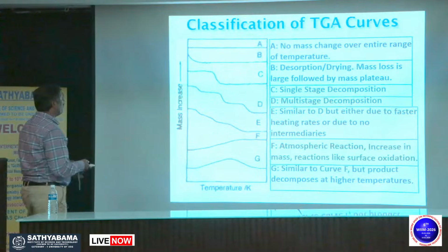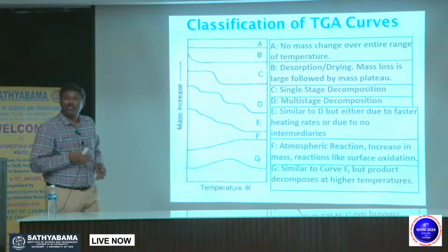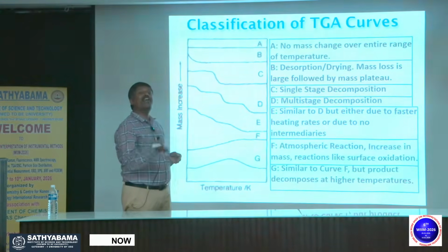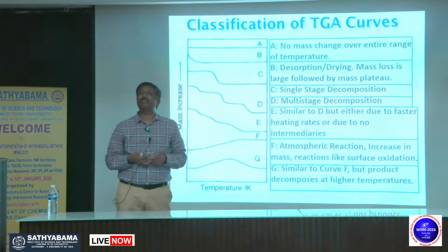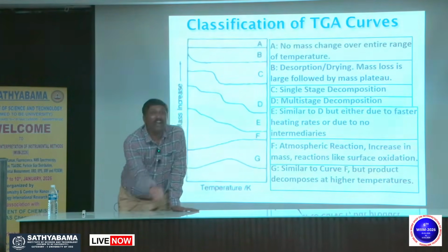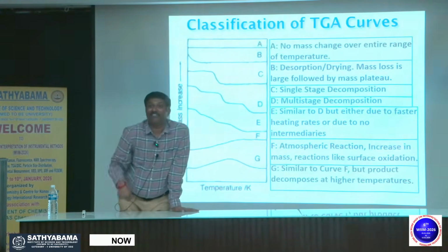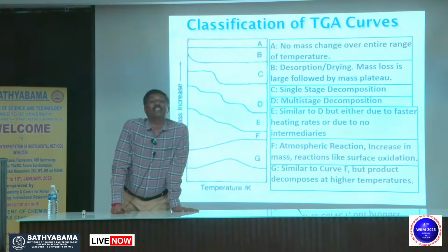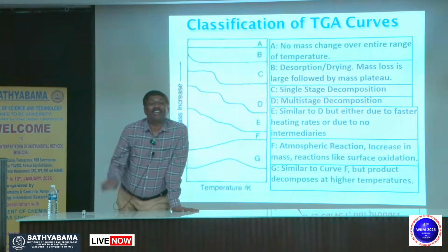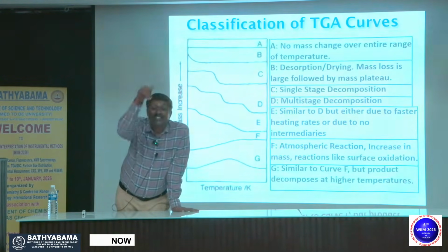Now, F you see, F. This is a miracle. Generally, it won't happen. With heating, temperature raised. With temperature raised, weight raised. How come it is possible? See, you took some weight. It's not like a bank, it will give you interest. The reason is carrier gas. So the carrier gas interacts with the sample and makes additional products and settles there.